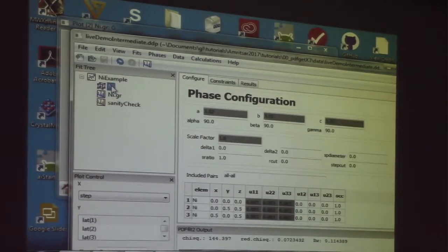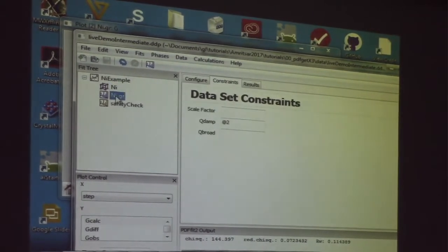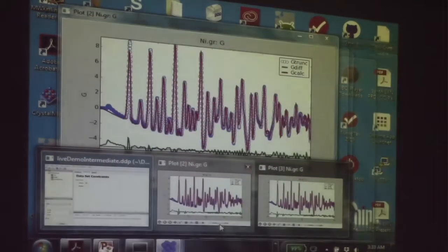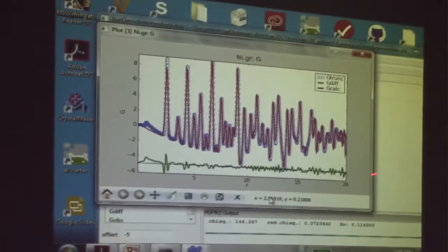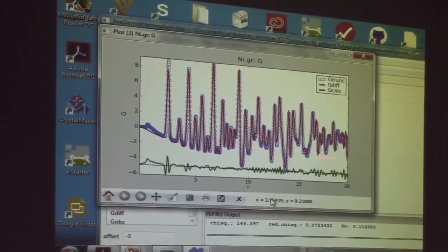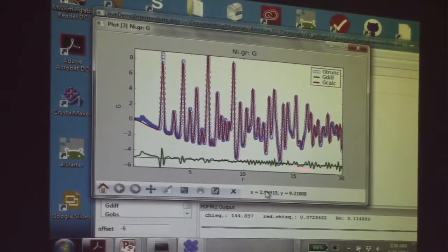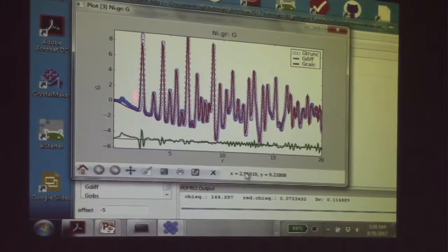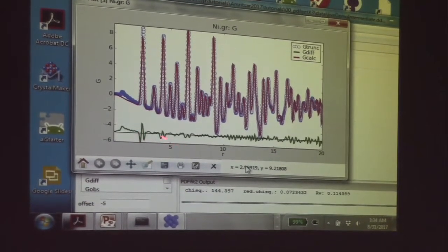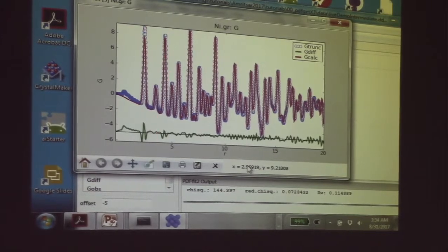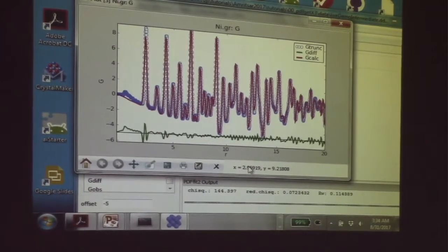So let's look at this again. You don't need both of these. So things are reasonably okay out here. This thing is going to need maybe a little bit of work later. But the low R peaks, a very interesting thing is happening, that the data peak is sharper than the model peak. This is actually a real physical effect.